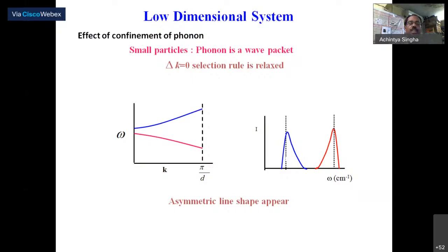If the phonon dispersion curve goes downwards with the increase of k, then we see an asymmetry in the lower energy side of the spectrum. And if the phonon dispersion curve goes up with the value of k, then we get an asymmetry in the Raman spectrum on the higher energy side, as you can see from the picture on the right side. Okay, go.